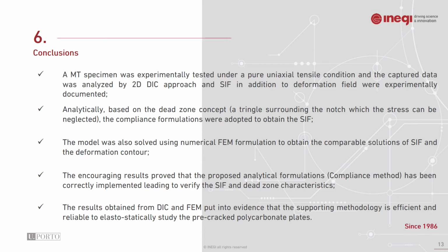And the encouraging results prove that the proposed analytical formulation, which is based on the compliance method, has been correctly implemented, and the stress intensity factor and the dead zone characteristic were verified. The results obtained from digital image correlation and finite element method put into evidence that the supporting methodology is efficient and reliable to elastostatically study the pre-cracked plate, and in this case it was used for polycarbonate.